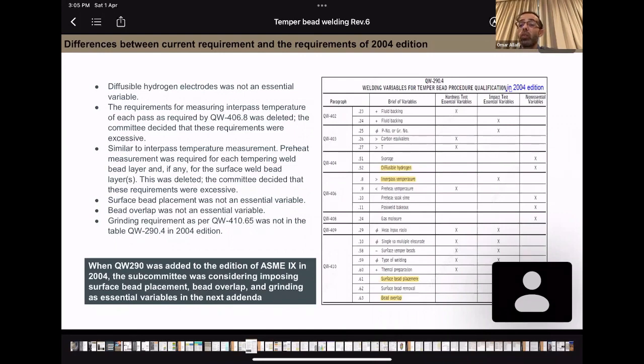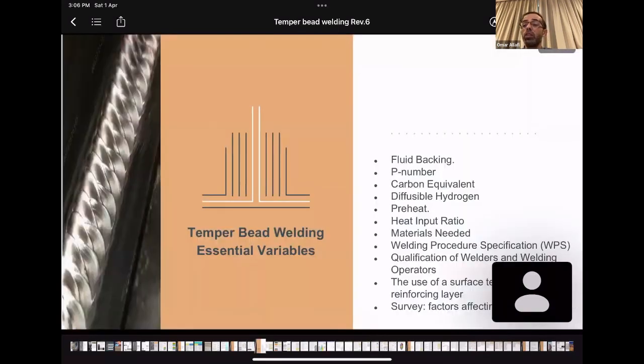And the grinding requirement was not in the table. So it's not that it was not an essential variable; it was not considered in the table. But there was a note when they adopted this. The ASME Section 9 subcommittee was considering imposing surface bead, bead overlap, and grinding as essential variables in the next edition. And they were added in the 2006 edition.